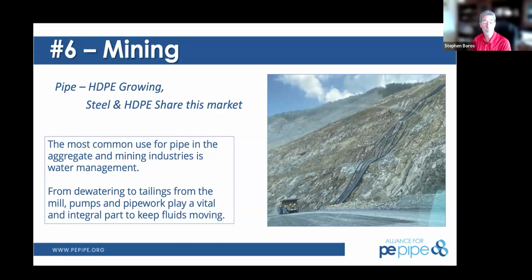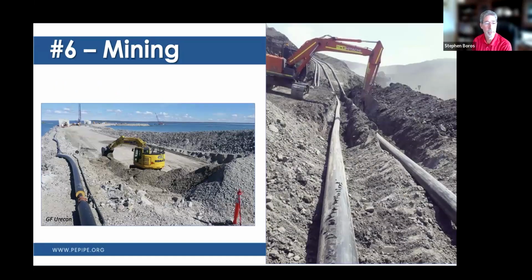Yeah, that's a good point. So polyethylene is used much more than steel in these applications. Again, because of its toughness, even if the particles fall out of suspension, which they do a lot of times, and it can cause significant abrasion. They found that polyethylene pipe lasts from 4 to 10 times longer than steel, depending on the type of aggregate and how abrasive it is in these applications, simply because the particles tend to bounce off of it rather than score it and gouge it and erode it over time. So dredging, mining, and things like that, they'll go to polyethylene 9 out of 10 times.